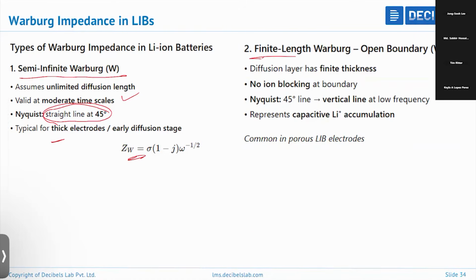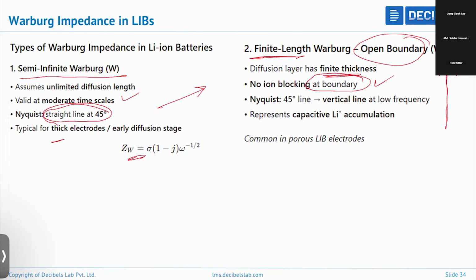And the second type is the finite length Warburg. It's actually the open boundary. So the diffusion layer has a finite thickness, no blocking at the boundary. So the lithium ion has, there is no blocking there. So if that kind of structure is there, with finite thickness and no blocking boundary, then that 45 degree line will form a vertical line parallel to the imaginary axis. It acts like a perfect capacitor, representing lithium ion accumulation. So this is common in porous LIB electrodes.